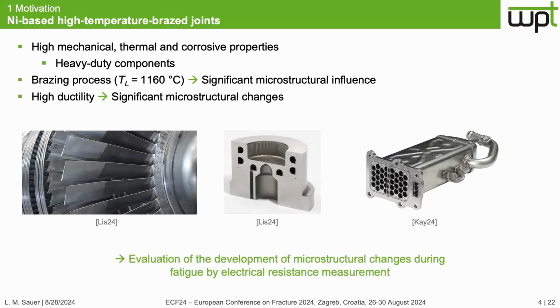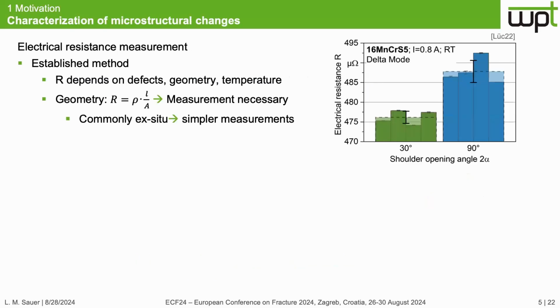Therefore, the goal of my work is the evaluation of the development of microstructural change during fatigue by electrical resistance measurements, so that the fatigue behavior of the brazed specimens can be optimized. Electrical resistance measurements are an established method for the characterization of microstructural changes like dislocation density, voids, or microcracks, because the electrical resistance depends on those microstructures. But the electrical resistance also depends on the geometry and temperature, and therefore it is necessary to measure the geometry and temperature too for the characterization.